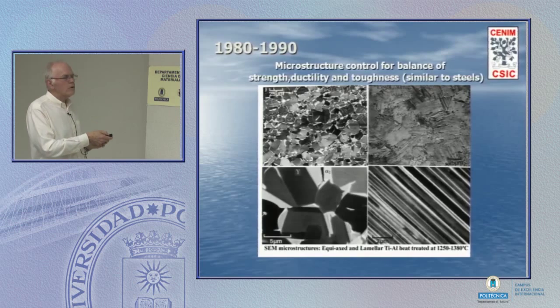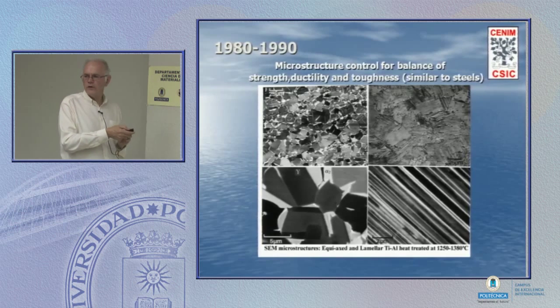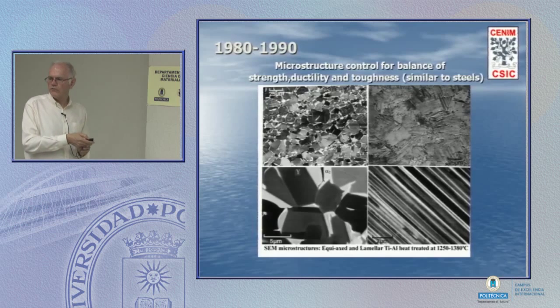Or if I cool very slowly, here I've got globular grains of gamma with, at the grain boundaries, large chunks of alpha-2. And it's very easy to heat up the material and heat again if I want to, heat up the material, cool down in a controlled manner to achieve this structure and these properties, or this and this.